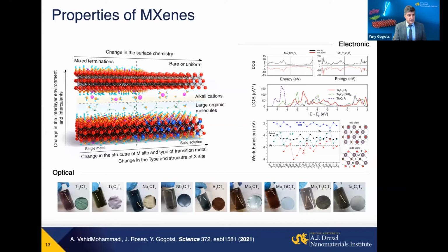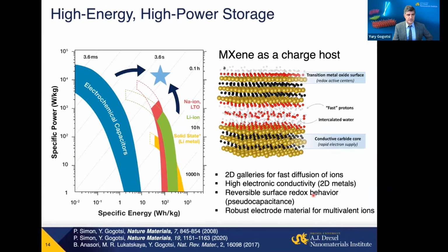And for example, just by changing surface termination from oxygen to OH, we can change work function from 6 to about 2 electron volts. And in a similar way, all other properties, including, for example, plasmonic optical properties, can be tuned. So again, this is where I mentioned there is some similarity to framework materials that you have heard about in the previous lecture of Professor Yaghi.